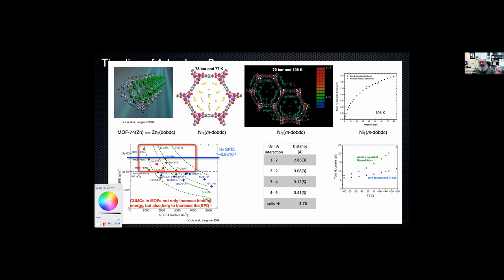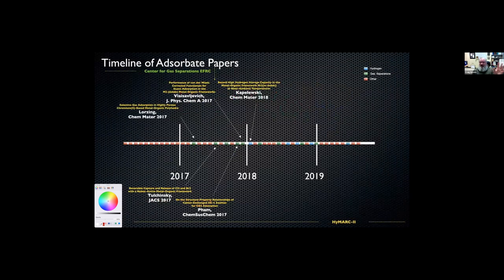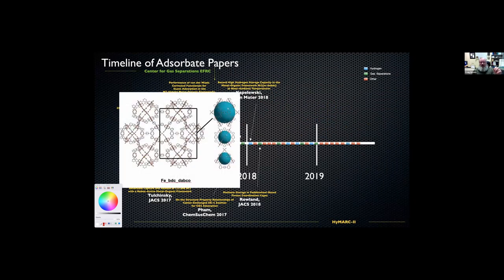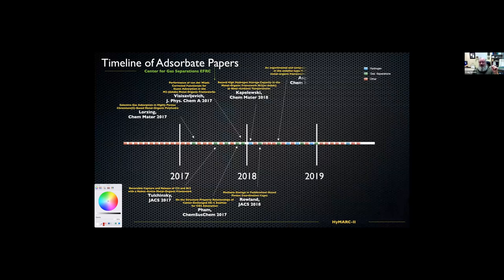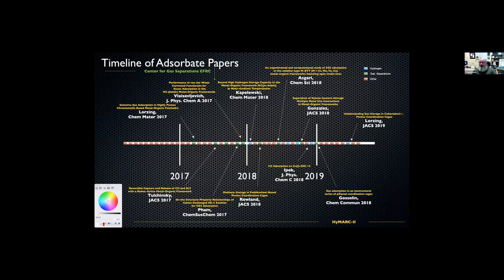We've looked at the different scattering at higher temperatures and the dynamics. One thing that I was always nervous to do was to look at real hydrogen inside those systems. We did that and proved that we could do it. We looked at some polyhedral cages like these, and here's an example of a script in Topas that allowed Ben to solve the solvated structure and slightly disordered structure here. You can see it's a lot of work, but we wouldn't have been able to do that if it wasn't for those capabilities and Ben's ability.